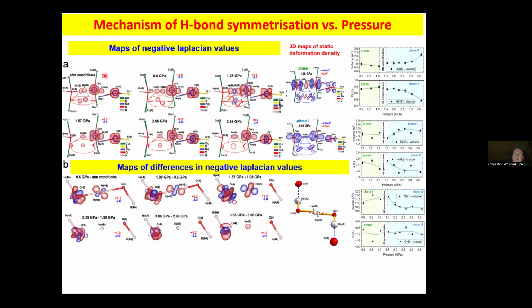We can look at this using negative Laplacian maps or differences in negative Laplacian maps. In these negative Laplacian maps, we see at ambient pressure and at 0.6 gigapascal, clear two maxima confirming this disordered nature of hydrogen bonding. And when we increase pressure, we see depletion of electron density from this central point. And when we increase pressure more, these hydrogens localize at the center of symmetry, and with further increase of pressure, we have just more and more electron density at this point. Finally, a very strong ionic hydrogen bonding is created.